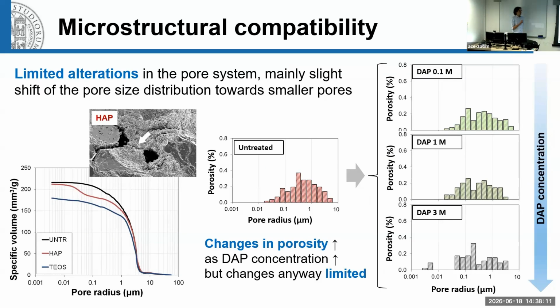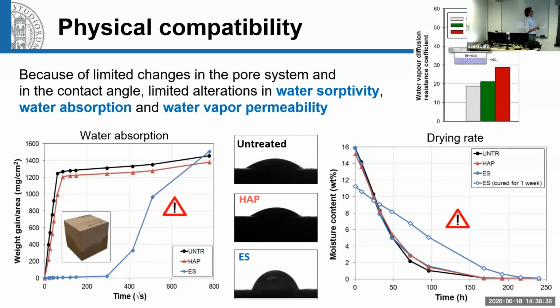Microstructural compatibility is not the only requirement. We also need to check what happens in terms of porosity. We are introducing something into the pores, so for sure there will be some reduction in open porosity, some alteration in the pore size distribution, as we assessed here by mercury intrusion porosimetry, but overall the changes are low, so they are acceptable. As a result of the changes in the pore system, also the ability of the stone to exchange water and water vapor with the environment changes to a certain extent.